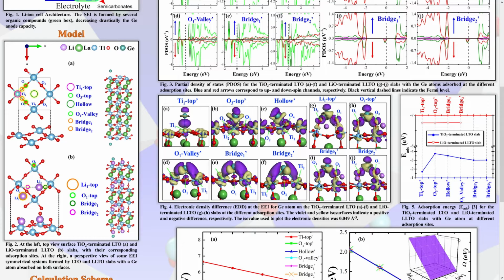From G to J, for the case of the lithium oxide termination, after the geometric optimization, the germanium moved seeking to interact with two oxygen atoms in all cases. Again, charge transfer suggests the formation of germanium-oxygen covalent bonds.